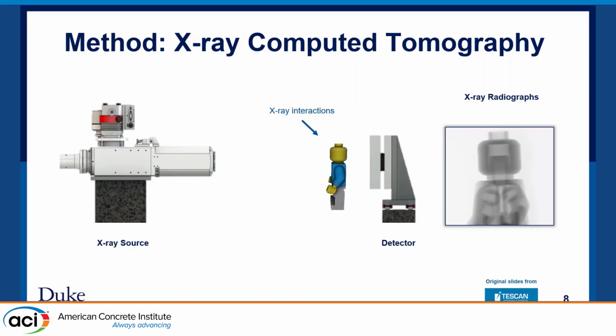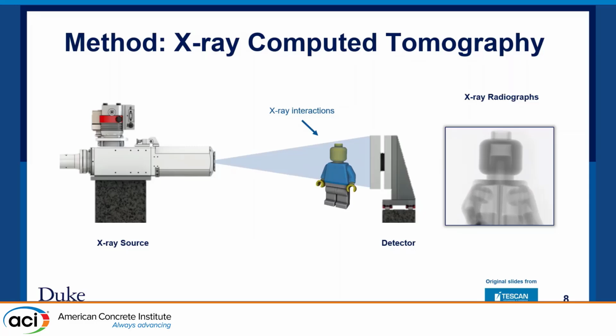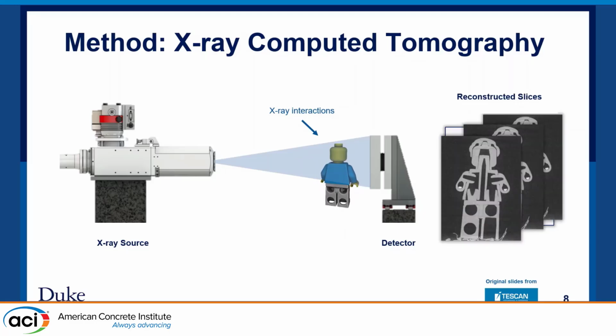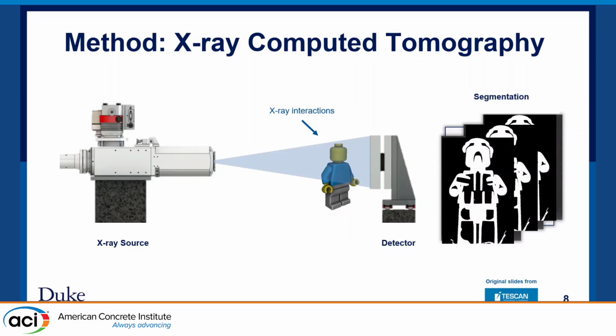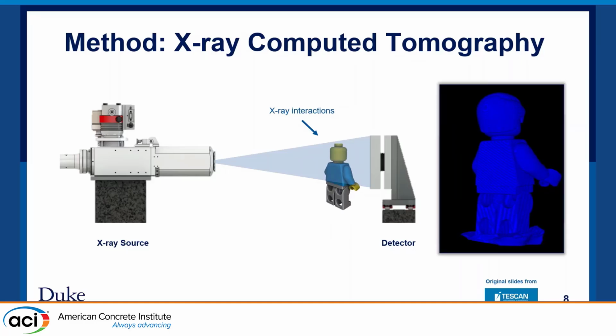So this setup has an X-ray source and a detector facing each other, and the sample that is to be scanned is kept in between those. When the X-ray passes through the samples we want to scan, we get different X-ray radiographs that we can reconstruct and segment and get the results that we want to see. Also, we can get the 3D modeling of the samples that are being scanned.